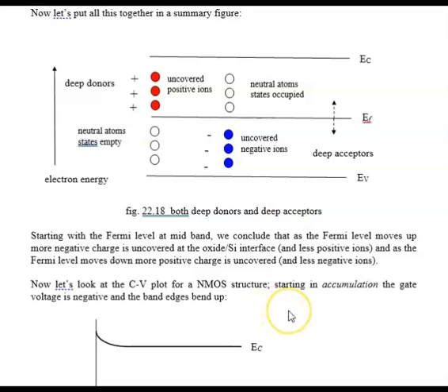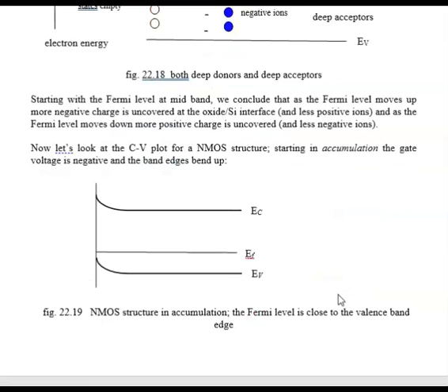So now let's look at the CV plot for an NMOS structure. So in NMOS structure, I have P silicon in the bulk. The Fermi level is close to the valence band. In accumulation, it's even closer to the valence band. I have a negative voltage on the gate, and this would be an energy band diagram for the NMOS structure. In accumulation, the bands bend up a little bit, so the Fermi level should be even a little bit closer, but it's reasonably close. It's certainly below intrinsic. Intrinsic is up here, so it's close to the valence band in the bulk. It is really, really close to the valence band in accumulation.